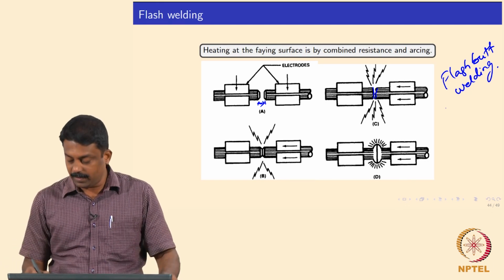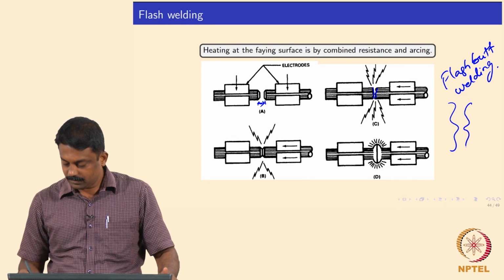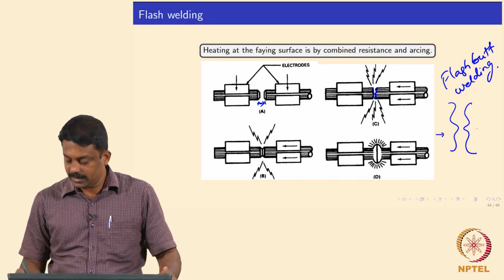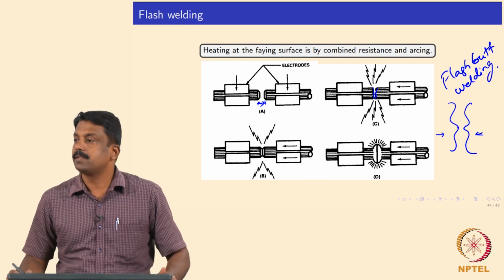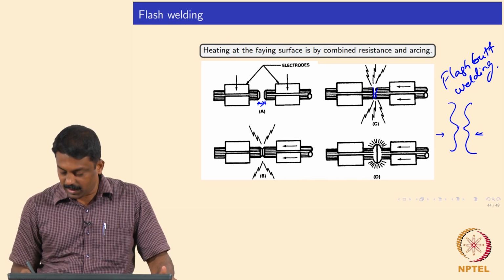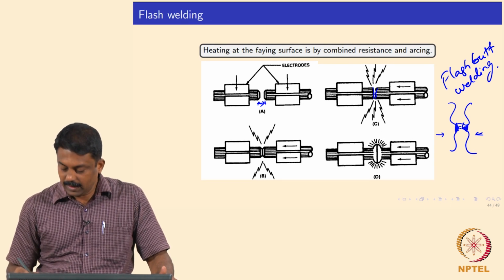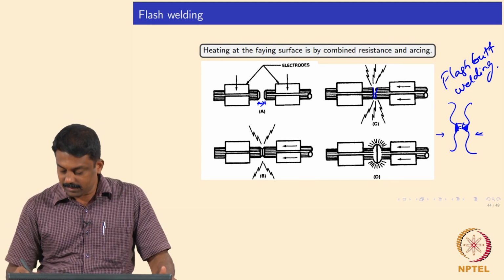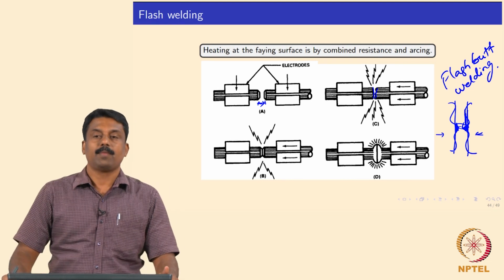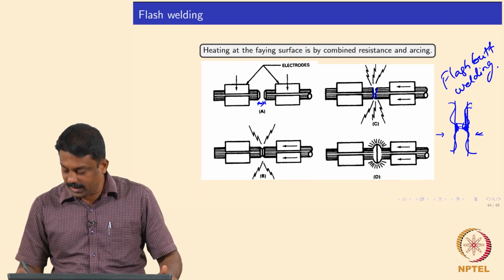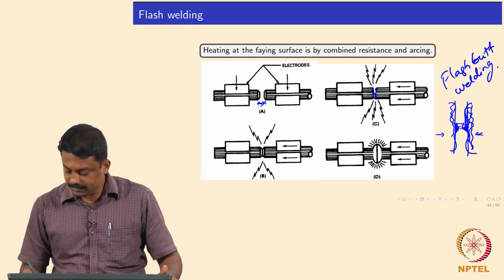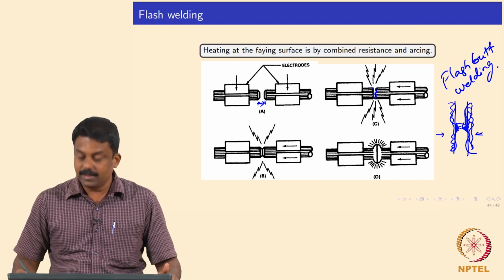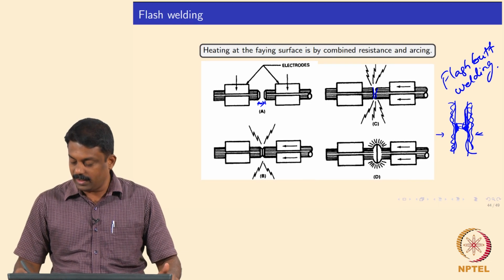The first melting would take place at, for example, this surface roughness point. When you pass a current, obviously this point would start melting first, isn't it? It will form an arc, and once it melts it will explode, and then it becomes slightly flatter. Similarly the next point would arc and melt and explode, and the remaining parts next will melt, and ultimately you make a more or less uniform interface, isn't it? During this process you also heat the adjoining areas to higher temperatures, because you are melting the interface. Obviously the regions next to the molten layer would be at very high temperature.